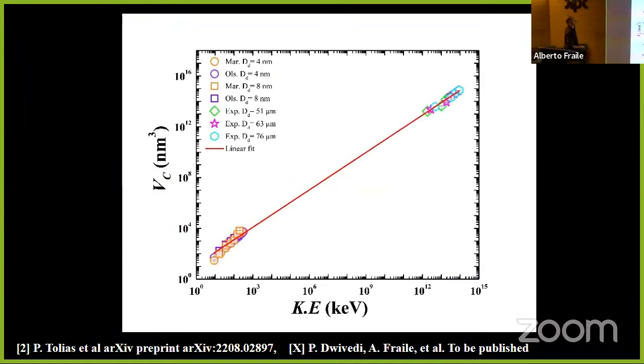Then if we compare to the experiments, here we have all our MD results, and here the experiment. It looks good to me, but someone can say that you have a big gap here, a lot of orders of magnitude, and it's true, because the velocity is the same, but not the kinetic energy, because of the size of the impacting particles. So you can say, okay, you have a point here and a point here, and then you can pass a line, fine.